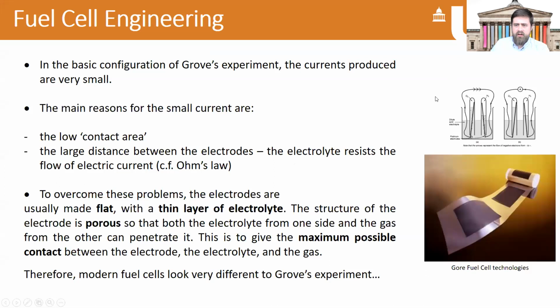Right, so we've gone from this basic configuration of William Grove's experiment some 200 years ago with two flat electrodes. And the current that was produced in these experiments is actually really very low, and that's because there's a very low contact area or low surface area, and actually a large distance between the electrodes as well. Okay, so the electrolyte itself has a resistance associated with it, and you want to minimize that. So to overcome that, there's been a lot of development in fuel cells over the last few hundred years, and in particular the last 10 years or so, mainly centered around making very porous, very high surface area electrodes and very thin electrolytes, and moving away from these liquid or aqueous-based electrolytes to a solid electrolyte, which is a polymer electrolyte, which we'll talk about in a little bit more detail soon.